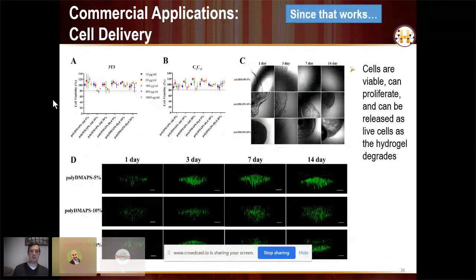We've also seen that these materials, particularly the zwitterionic materials, are really good for delivering cells. And we didn't anticipate this because a lot of these protein repellent materials are also cell repellent. As such, you can keep cells happy in the gels for a few days. But typically, because they can't adhere well, over time, they get a bit stressed out and they start to die. That doesn't seem to be the case with these zwitterionic hydrogels. And we're still trying to figure out why.